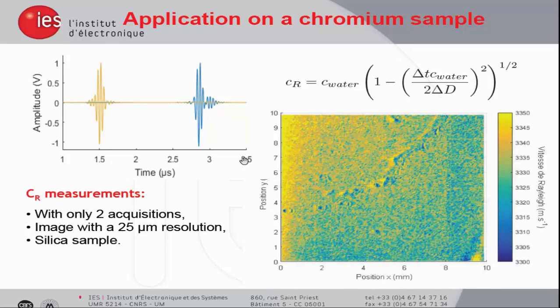So what we did is, first we tried to validate our method by proposing a protocol to allow the imaging of the material properties with only two acquisitions. So here you've got the acoustic signals that were received on a silica sample, that is a highly homogeneous sample, at two different vertical positions of the sensor. And by this simple equation linking the vertical distance between the two positions and the time delay between the two samples, then we can recompute the Rayleigh velocity. And here is an image, 10 by 10 millimeters, with a resolution of 25 micrometers, meaning that we've got 400 pixels here, an image of the Rayleigh velocity of the silica.